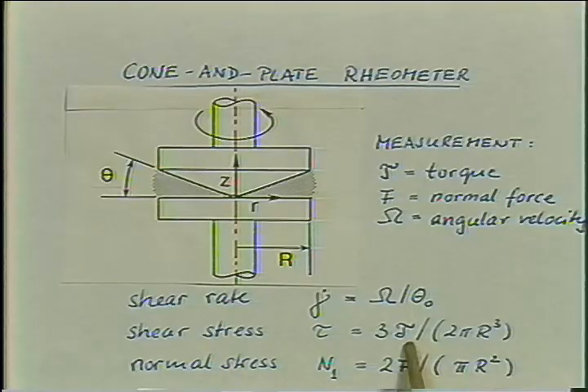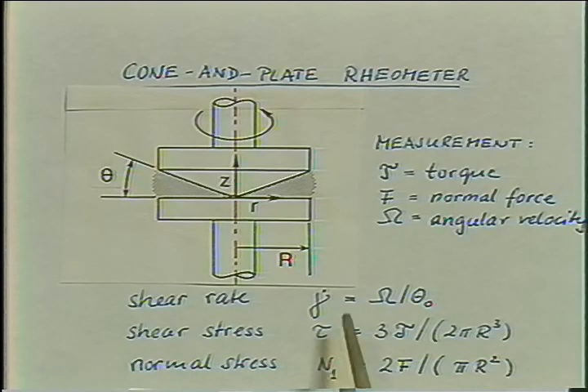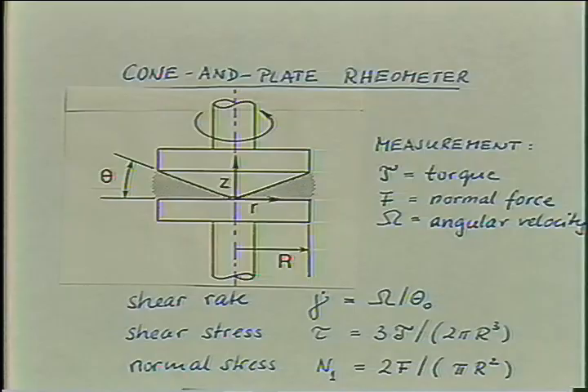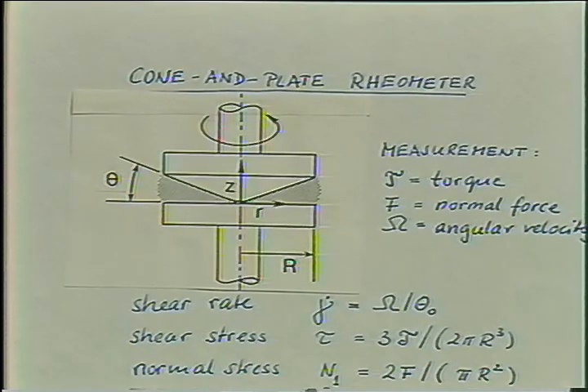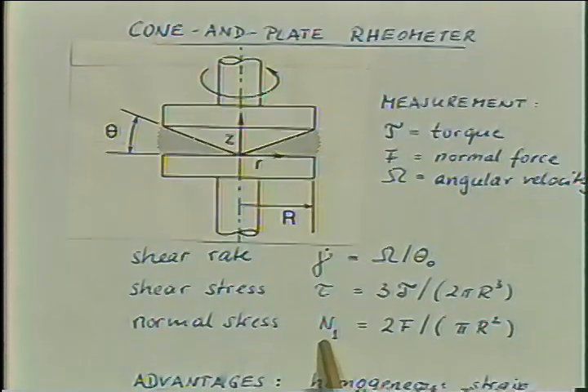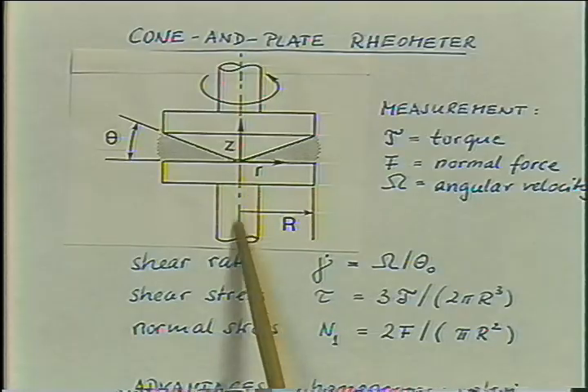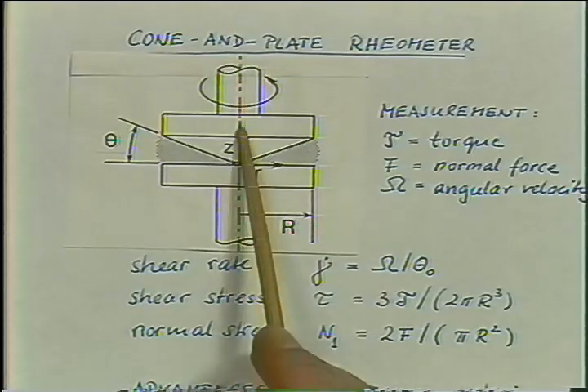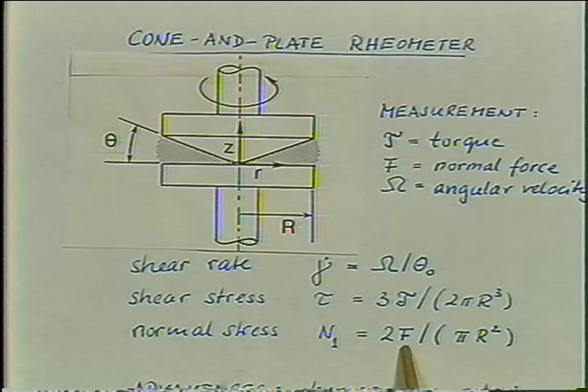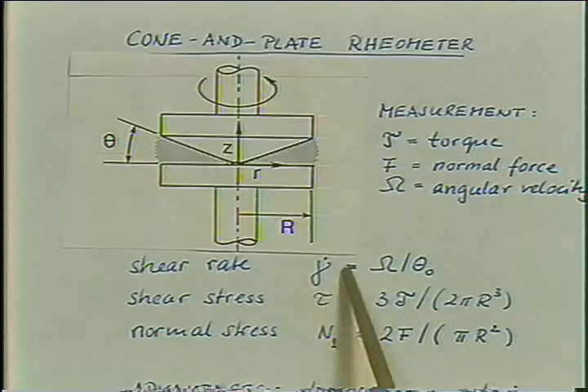The shear stress is proportional to the torque of the material, and again, it's available in the whole sample. What a luxury compared to capillary rheometry, where we only got the shear rates near the wall. Here we have the shear rate throughout the sample and the shear stress throughout the sample. The normal stress is giving rise to a separating force, a total force which is pushing the plate and the cylinder apart. And this force is being measured, and from that we measure the first normal stress difference at the imposed shear rate and get another interesting piece of information.